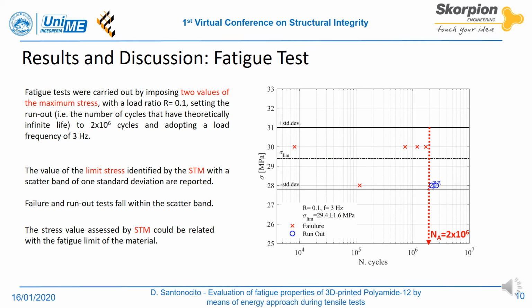A series of fatigue tests has been carried out with a constant stress amplitude equal to 28 and 30 megapascal. The test results are reported in an S-N plot adopting a number of cycles for runout of 2 million. In the same plot are reported the average value and the scatter band with one standard deviation for the limit stress assessed by the static thermographic method. As it is possible to note, both failure and runout tests fall within the scatter band, hence the stress value assessed by means of the static thermographic method could be related with the fatigue limit of the material.